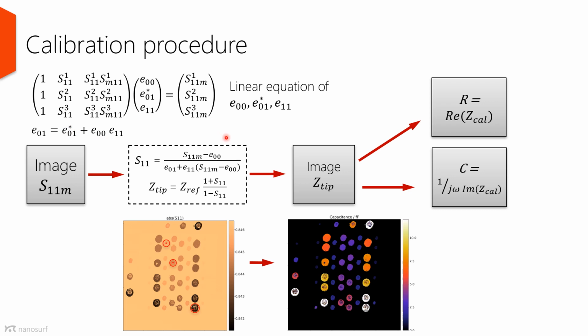Then we apply this calibration procedure in reverse order, and from the measured S11, we determine the map of the impedances, and from the impedance map, we calculate the map of the capacitances. And the values of the capacitances we just calculated are in very good agreement with the measurements done by other groups. The same calibration procedure can be done when measuring the dopant density. It would just require one extra step, the calculation of the dopant density from the capacitance.